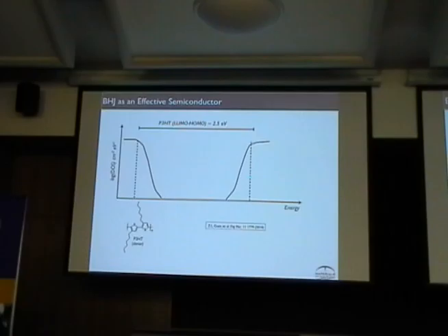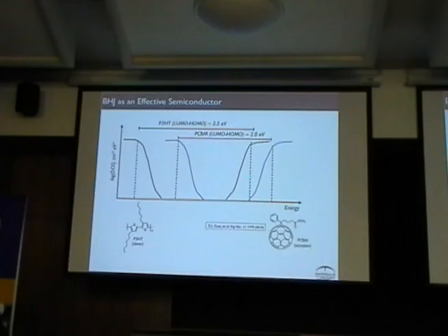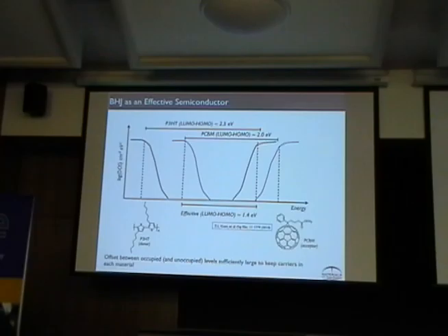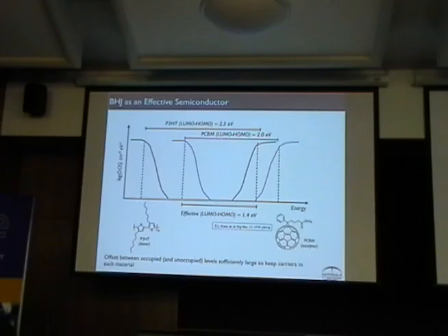If I want to treat this bulk heterojunction — I just mix those two things together — we have P3HT. There's a difference between the HOMO and the LUMO. If I take PCBM in an isolated case, I have a HOMO and a LUMO for that one. The charge carriers will just find the state here; the LUMO will drop in energy to the LUMO of PCBM. The holes will go uphill to the HOMO of the P3HT. So I have an effective band gap that's a composite of those two materials.